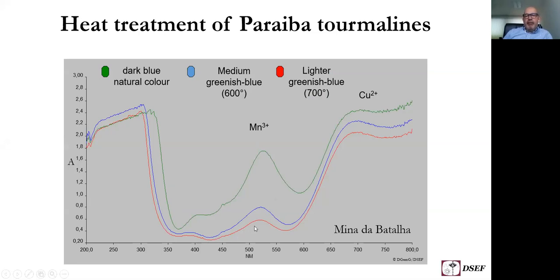But there is still some manganese present, so the presence of a small manganese absorption band is not necessarily proof that the stone is unheated. So it's very difficult to identify whether a Paraiba tourmaline is heated or not, and in many cases it is simply not possible.